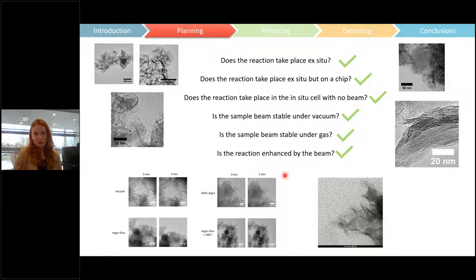There is a little trick you can use to bypass the fact that your beam may be influencing somewhat your particle growth or the reaction that you're expecting to see. And that's to work way above the temperature at which your reaction would normally happen. Because when you're far, far above that temperature, you get the added benefit that the beam's contribution to the reaction is very minimal compared to the thermodynamics of working at such a high temperature. That's one nice way to bypass it a little bit, still acknowledging the effect of the beam, but getting some slightly more reliable data: work at a higher temperature than you want, so that your beam contribution to that reaction becomes negligible compared to the contribution of the actual thermodynamics from the heat itself.